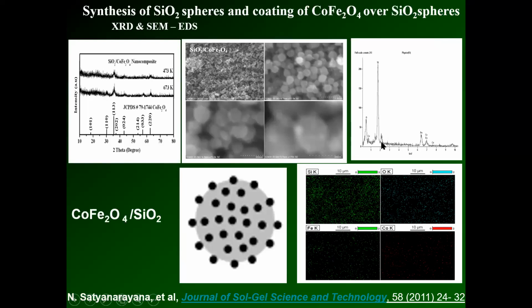You can see that previously the EDX, energy dispersive spectroscopy spectrum, consisted of only silicon and oxygen. Now, apart from silicon and oxygen, you have iron and cobalt. So definitely this is the nanocomposite. You can see that the cobalt ferrite particles are not continuous, they are deposited.